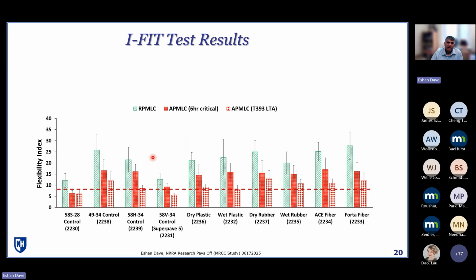IFIT, or Illinois Flexibility Index Test. As I'd mentioned earlier, there are three sets of columns here. The first one is again reheated. The second one is the standard NRRA agreed upon aging condition, 6 hour loose mix, 135 degrees Celsius. And then the third bar is what Illinois DOT is using for their long-term aging for IFIT testing, where it's essentially aging done for multiple hours at 95 degrees Celsius on a compacted flexibility index test specimen prior to testing.